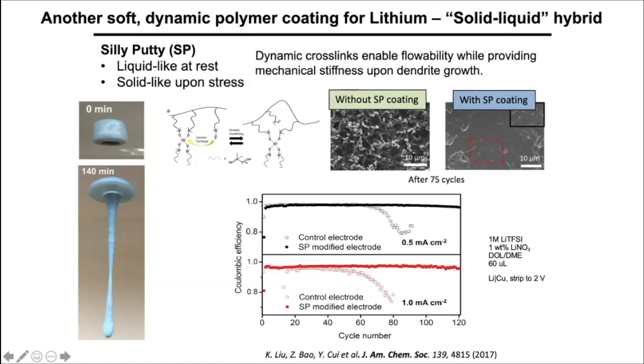And we were also happy to see that another student, a postdoc of Yi's, took another flowable, dynamic polymer. And this one has the boron oxygen bond that's dynamic. And again, this polymer shows that with the coating, it grows the nice plate-like structure and starts to give much improved cycling for the lithium metal.